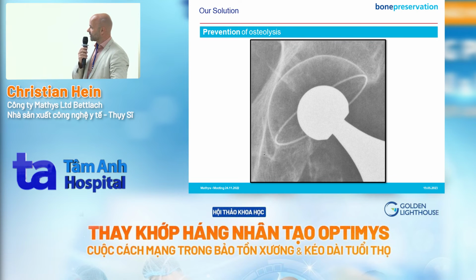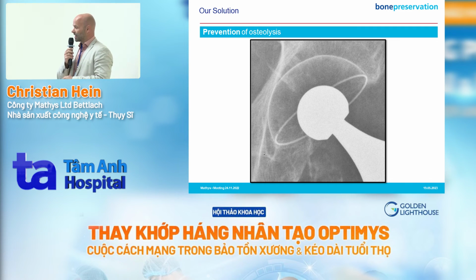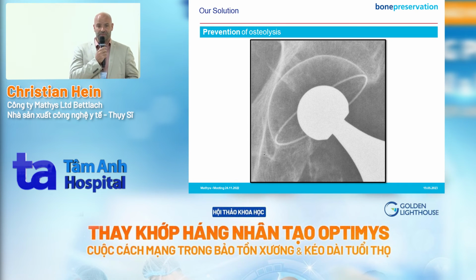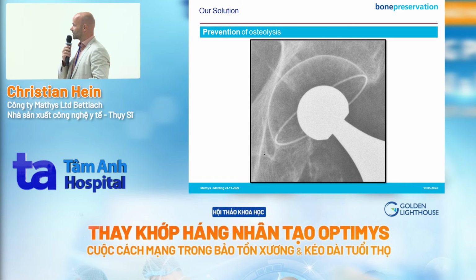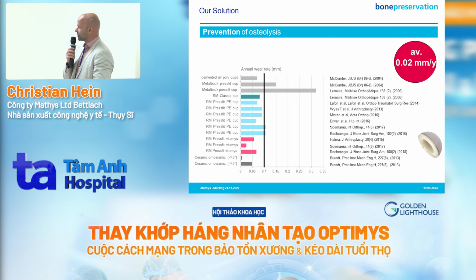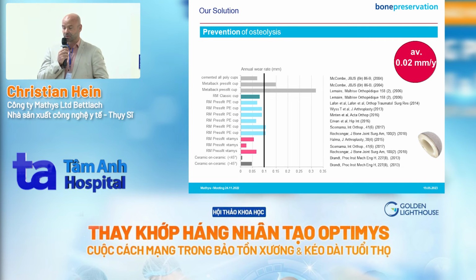With RM, as you're going to have only a monoblock cup, after 1 year, you can already see how the trabecular structure gets back onto the bone, onto the cup. It recovers the bone, and it means in case you have to revise a cup like this, you actually can use a primary implant again, which is much better than what you have with modular cups. That's what we could see as well on this picture, that we can reduce the wear and osteolysis with RM Pressfit, which would then be similar to ceramic on ceramic.